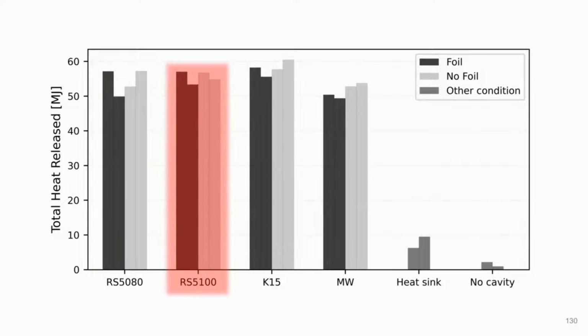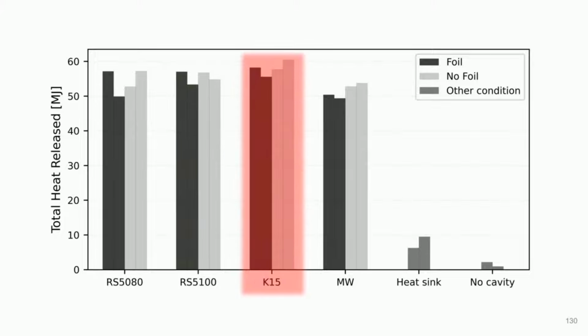The same is true, in broad terms, for the Celotex RS5100 product, the 100 millimeter thick Celotex product, and for the Kingspan Cooltherm K15, although in this case there does appear to be slightly more heat release in general. This is likely a result of the ongoing smoldering and flaming that I commented on when we looked at that experiment a few minutes ago.